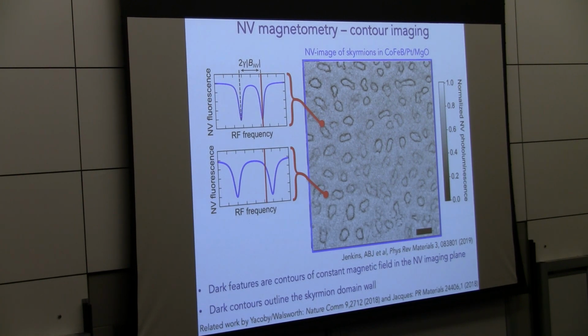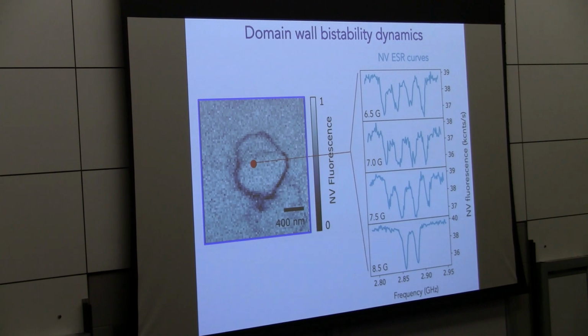Clearly, the most obvious thing here is that they're not round like the cartoonish pictures are. Again, this is an indication of there being local inhomogeneities in the sample. Moreover, if we zoom in on one of these skyrmions, we see this domain wall. If you look closely, you can see there's a domain wall here, but there's also a faint outline of another domain wall here.